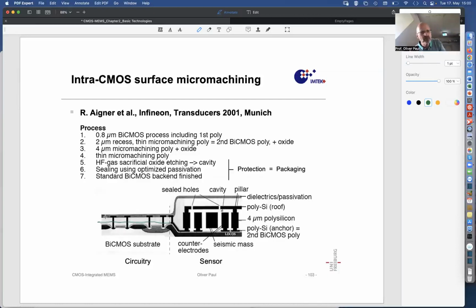And then you do another deposition, for instance, this thick dielectric layer on top of everything, plus some metallization and a passivation layer. And then the micromachine structure is totally encapsulated. Very handy. And you have done the job of encapsulation as well. It's always a challenge with micromachine structures. How do you handle them? Or let no dust go on them, because if you encapsulate the dust with it, then they won't work, and you have done all the work without a result. So this does the job, and thereby the CMOS process, or BiCMOS, bipolar CMOS process, is finished at the same time. So quite an interesting approach.